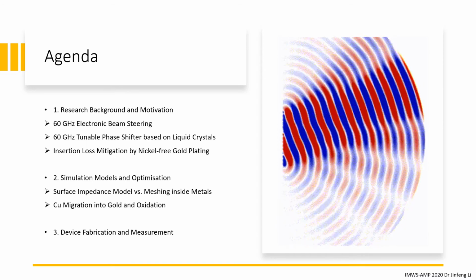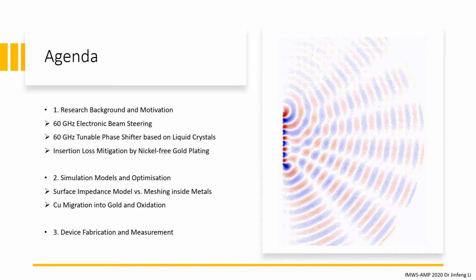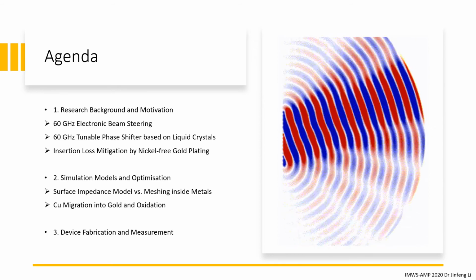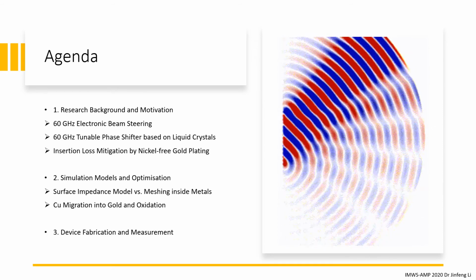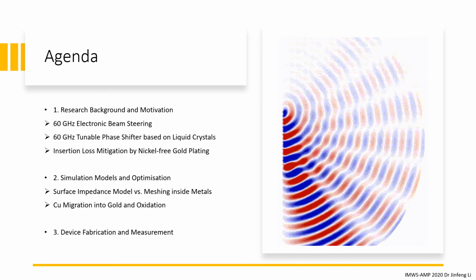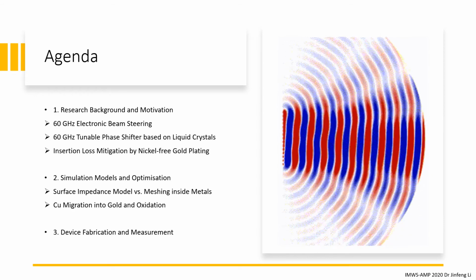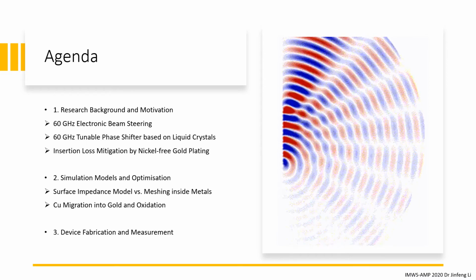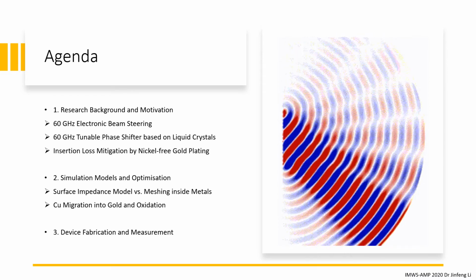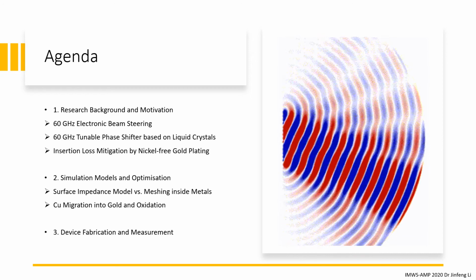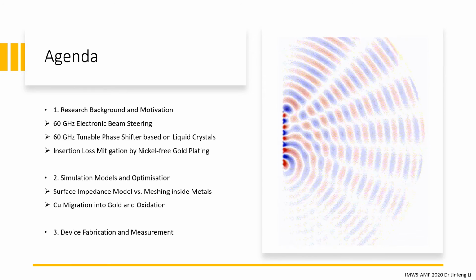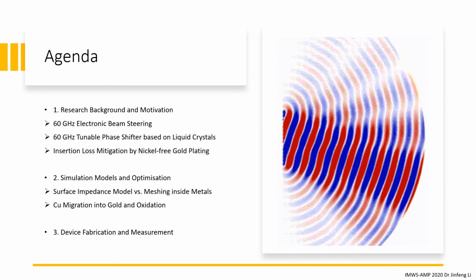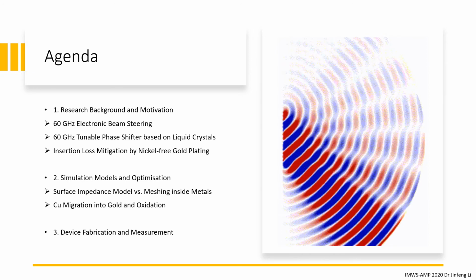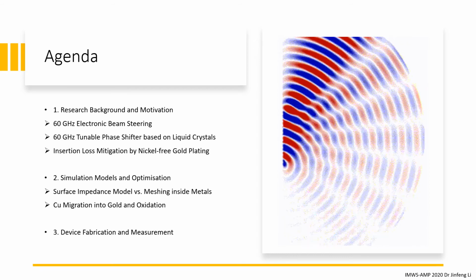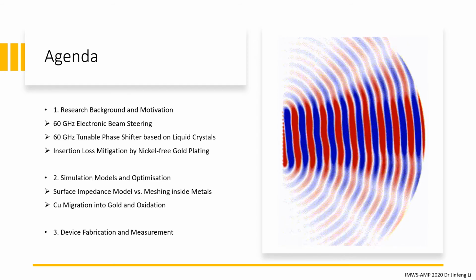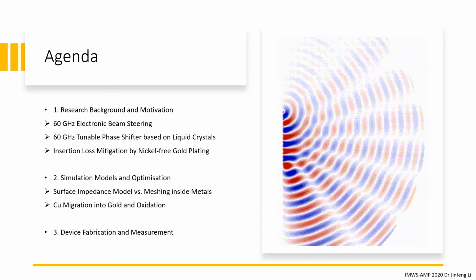During the design and simulation, we compared the conventional surface impedance model without meshing inside metals versus the method with meshing inside metals, and we found that for conductor thickness well above the penetration depth, the surface impedance model is working fine with the advantage of a reduced computational burden. But for structures in which the penetration depth is of the same order as the plated conductor thickness, substantial errors occur in the loss estimation.